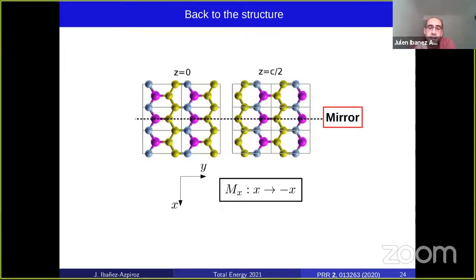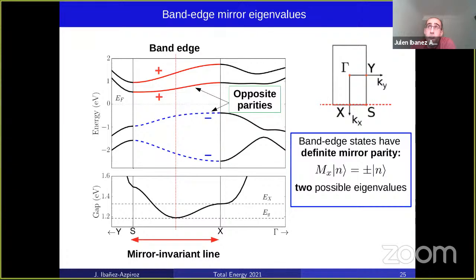Indeed, the crystal structure has a mirror reflection. It is mirror symmetric in the X coordinate. Because the bandedge lies at a mirror invariant point, the SX line is a mirror invariant line, and the bandedge lies there, this means that the bandedge states have definite mirror parity. And this parity can take on two possible values, plus or minus. In the case of BC2N, valence and conduction bands, shown here, have opposite parities.